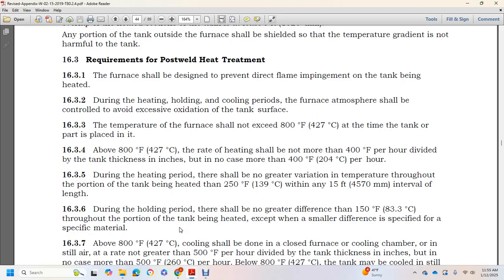The furnace should be designed to prevent direct flame impingement on the tank being heated during the heating, holding, and cooling periods. The furnace atmosphere should be controlled to avoid excessive oxidation. The temperature of the furnace should not exceed 800 degrees Fahrenheit when the tank and parts are placed in it. Above 800 degrees Fahrenheit, the rate of heating shall be no more than 400 degrees Fahrenheit per hour divided by the tank thickness in inches, and in no case more than 400 degrees Fahrenheit per hour.